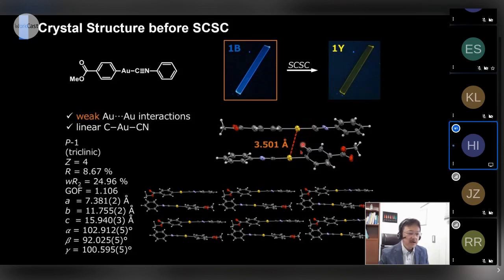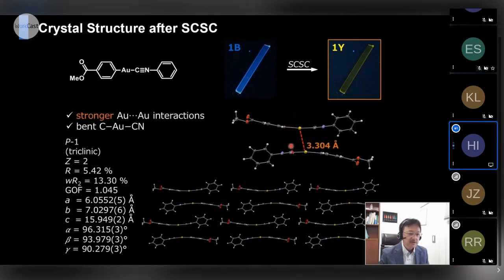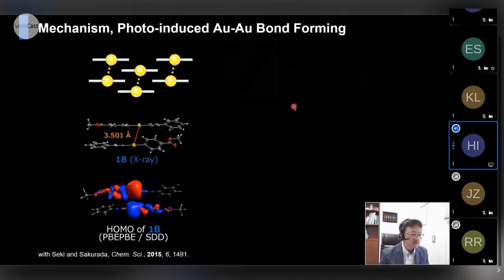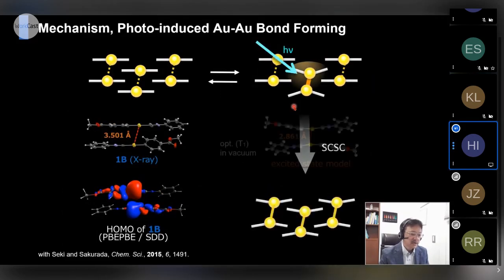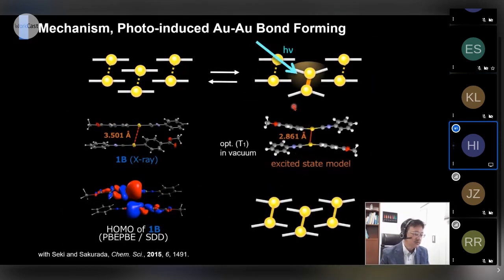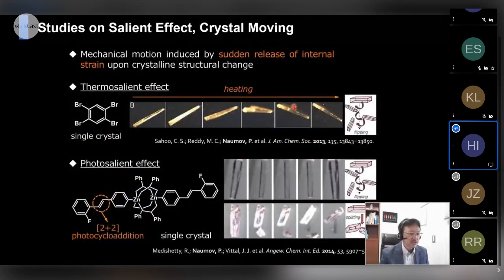This is the structure before the photoirradiation. And you can see after the photoirradiation, the structure was completely changed and the aurophilic interaction was drastically enhanced. We also studied the DFT calculation to understand the mechanism, but I'd like to skip this part because of the time limitations. So this crystal can show the so-called salient effect.